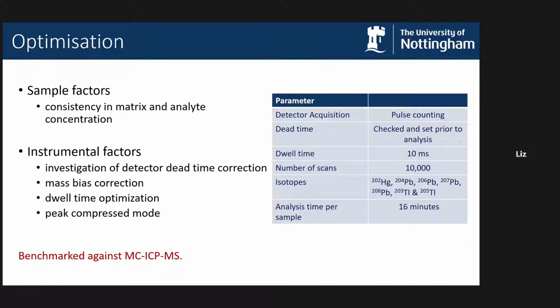And we varied that dead time correction factor until the value of the slope squared was minimised, and then we averaged it for each of the isotopes. And we did that before we used the instrument to make any isotope ratio measurements, so at the start of the day before any run.